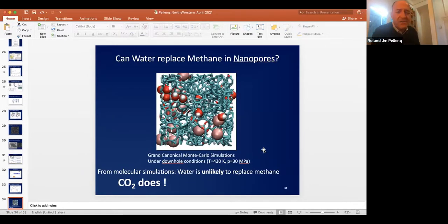And talking about prediction, we actually showed that those porous carbons love CO2. They don't like water so much, meaning that even if you calibrate with the pressure on the outside of liquid water at a pressure larger than the isostatic pressure in the field, the water will hardly get into the nanotexture of the Kerogen. By contrast, CO2 loves going there. And not only that, it actually displaces methane molecules. So 10 years ago, we were saying to the industry, you should use CO2 to stimulate the production of methane, because the current technology, which is based on water fracking, does not address the nanopores.